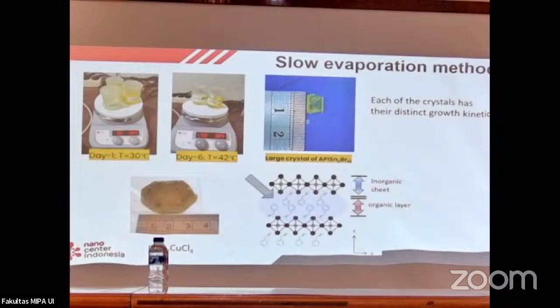To have this large crystal of this chemical structure, the API Sn2Br10 takes us a struggle of about 3 weeks. But it's really worth continuing, because this crystal gives us very good physical properties. On the other hand, some cases are quite relaxed. For this structure, the PEA copper chloride is much easier to grow, but you just need to be patient. This one takes about 2 weeks.